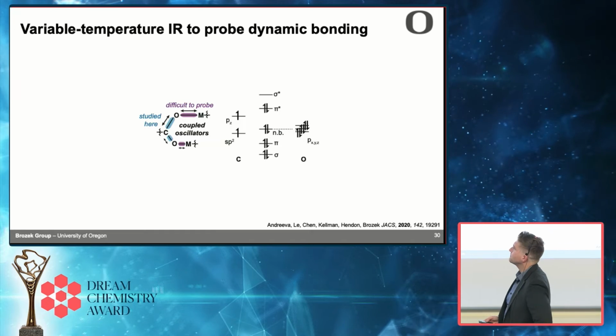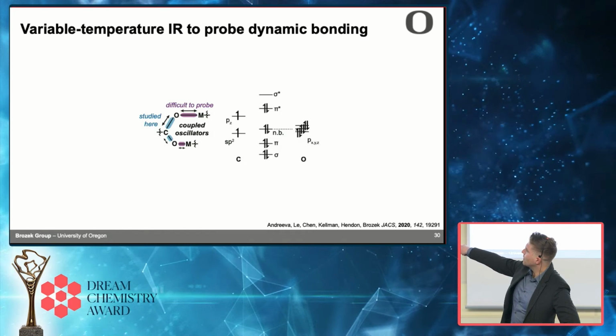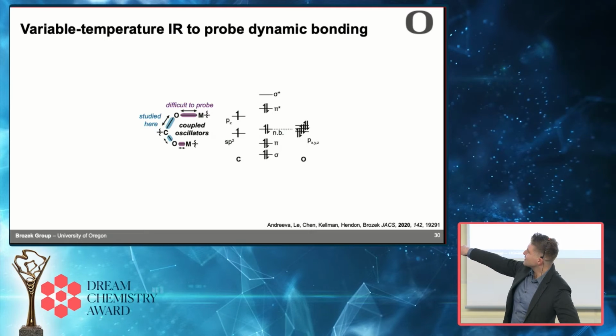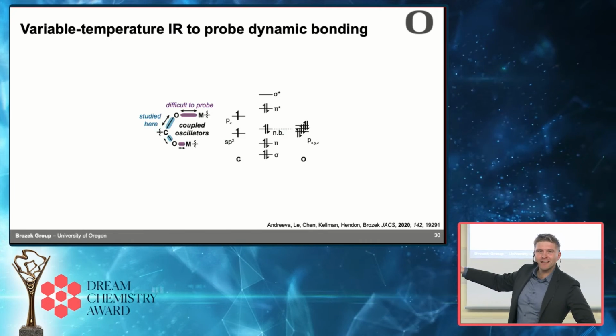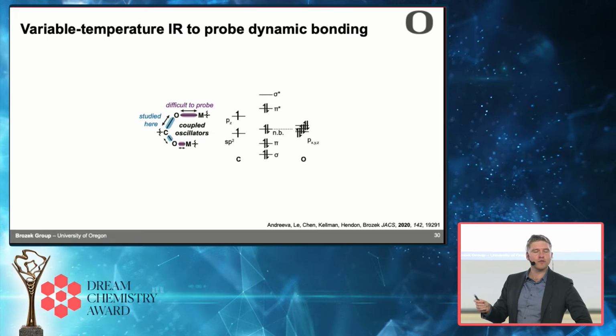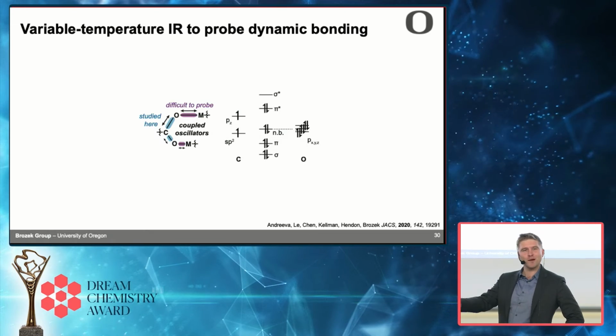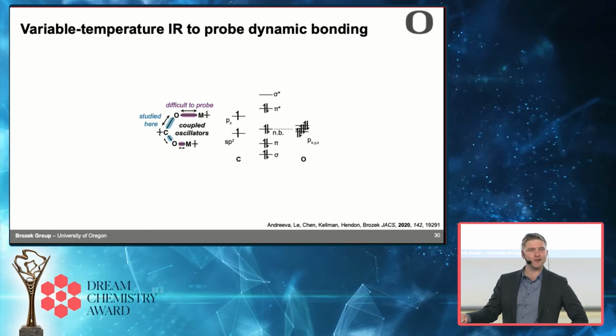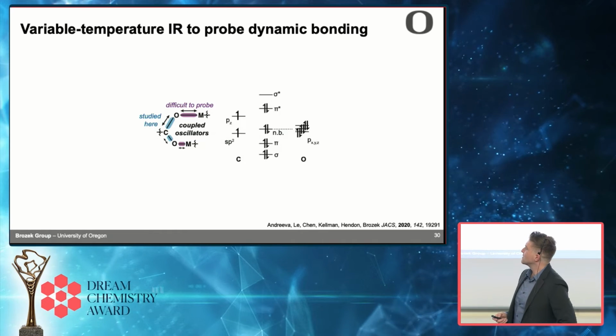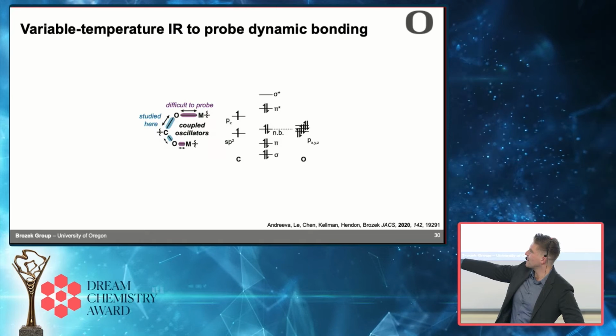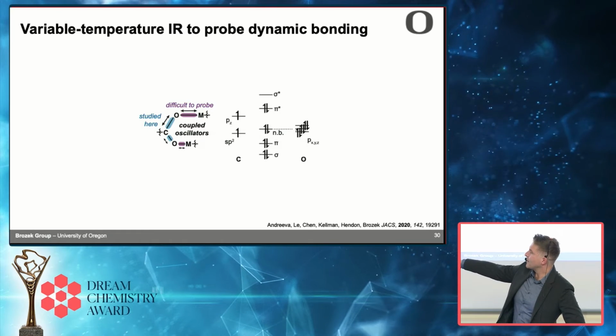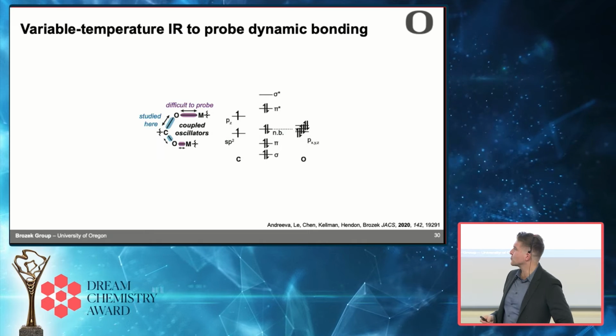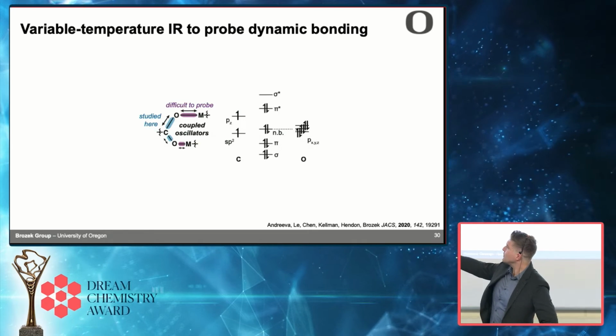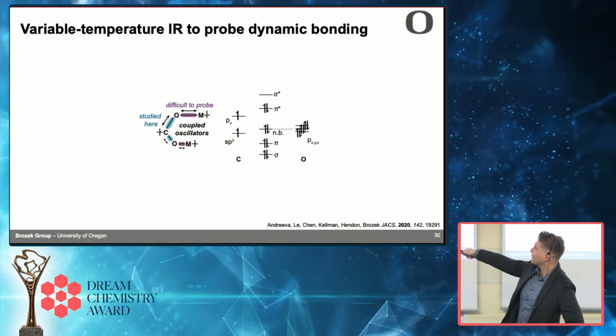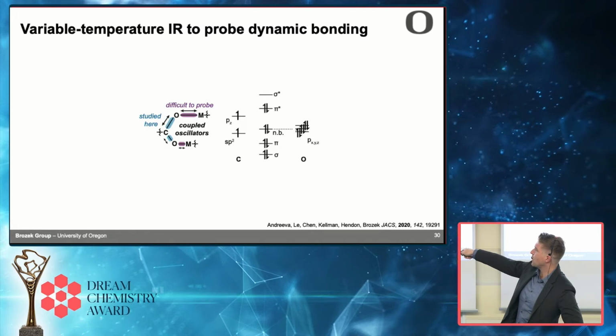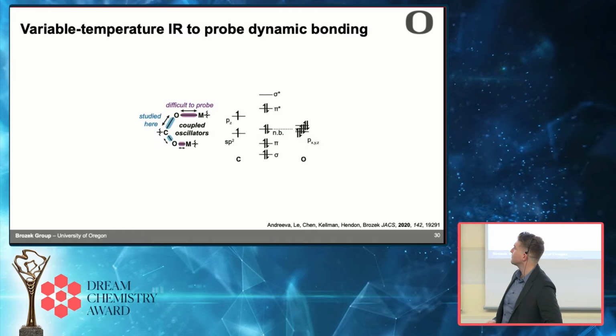And so my justification for that is these are the bonds that we want to see. These are the metal oxygen bonds we want to see. Unfortunately, the vibrations for these bonds are pretty low frequency, and you would need variable temperature Raman or variable temperature terahertz spectroscopy. I don't have access to that in my lab. So I figured, let's study this bond, the carboxylate bond, because this is going to be much more addressable with conventional IR spectroscopy. And I figured that even though this is not the metal ligand bond, a really big change to this bond should cause a small but detectable change in the carboxylate bond.